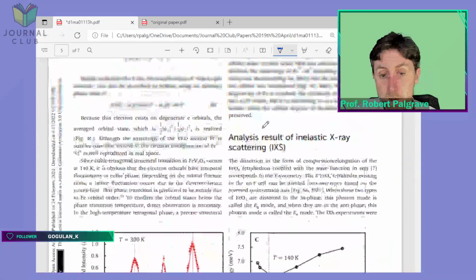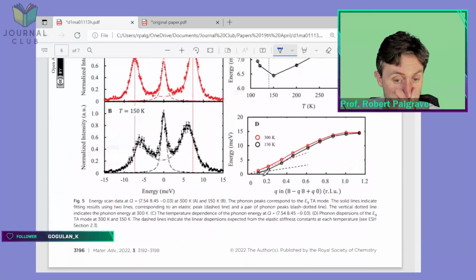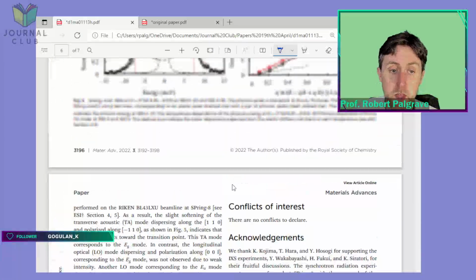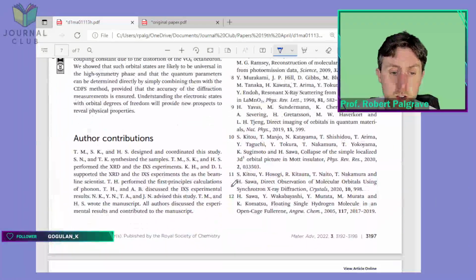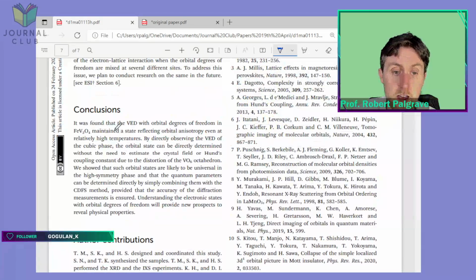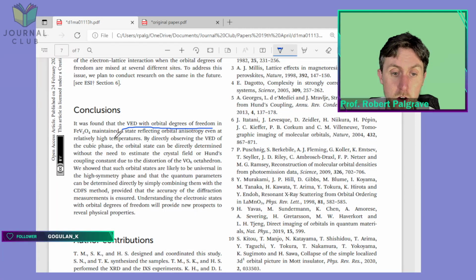There's a bit more of the paper. They also do a little bit of inelastic X-ray scattering. I'm not going to go through that part, but let's look at the conclusions. It was found that the valence electron density with orbital degrees of freedom in FeV2O4 maintained a state reflecting orbital anisotropy even at relatively high temperatures. By directly observing the valence electron density of the cubic phase, the orbital state can be directly determined without the need to estimate the crystal field or Hund's coupling constants due to distortion of the VO6 octahedron.